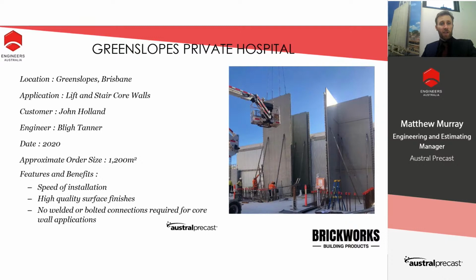Another successful project here recently is the Green Slopes Private Hospital that was completed in 2020 for John Holland in conjunction with Bly Tanner. So here we can see double height spin-up panels for a very large lift core and stair core for Green Slopes Private Hospital. So one of the main things here is the cores are much larger than a typical lift and stair core, and as a result, with the casting sizes that we were able to do double height, which is 3 meters in height for the 2 floors, and also 3.5 meter wide panels, which suited the size and shaping of the core. So the big advantage here is with double wall, there's no casting plates and there's no starter bar grout tubes compared to traditional precast.